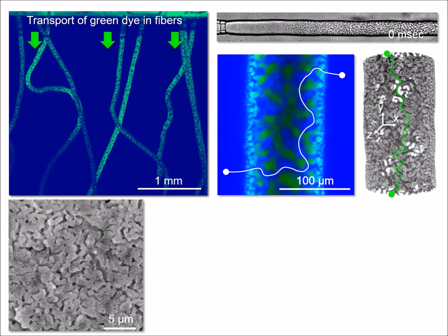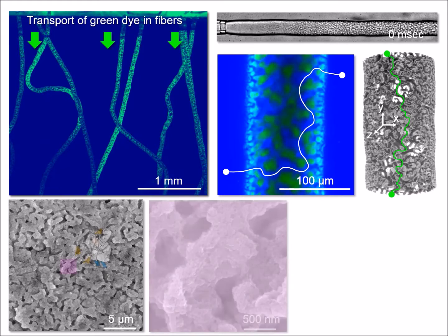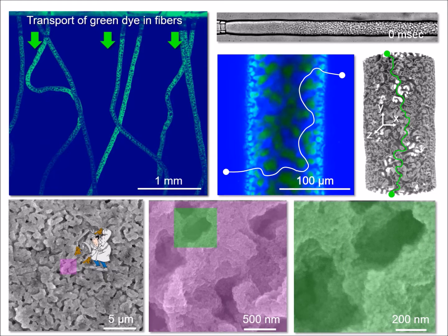What holds the oil-water channels in place is a thin film of nanoparticles. To see this thin film we use electron microscopy. Magnifying the surface up to 200,000 times shows that the nanoparticles have formed a densely packed crust with tiny holes in between them. This permeable nanoparticle crust can have catalytic properties to promote chemical reactions.